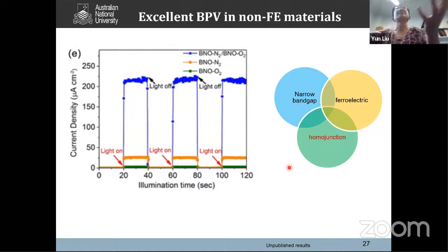Okay, of course, this is just the very beginning of the work, with only 10 nanometer thickness metal oxide. You put the two electrodes on to get this 1-2% power conversion efficiency, and it is quite good. If we optimize that, like optimize device structures, we can get even higher. Most important, because these kinds of materials are very stable, we can use them at high temperature, like for space technology, or different extreme condition environments.